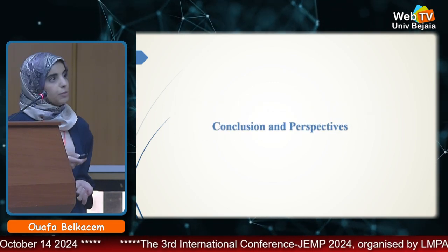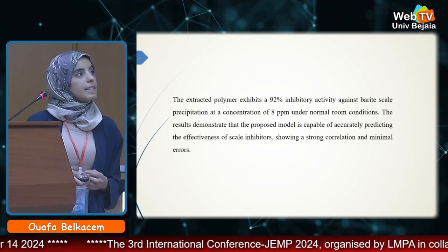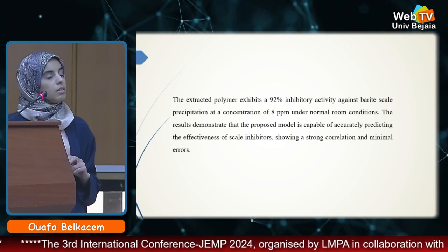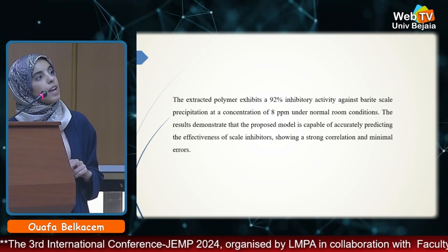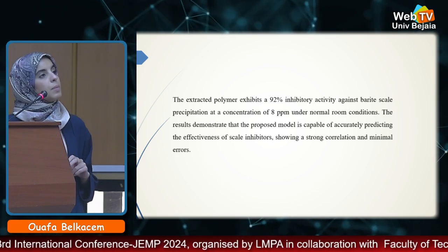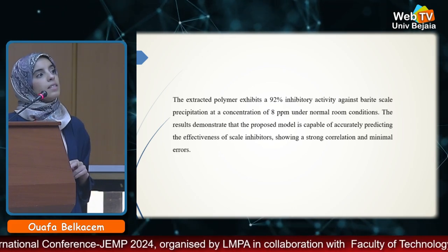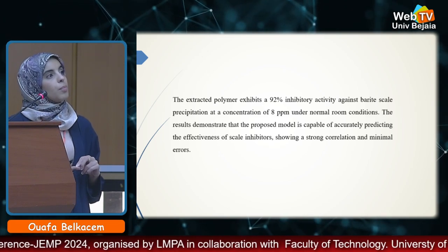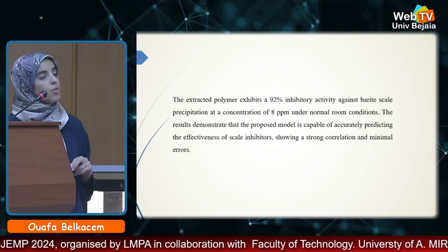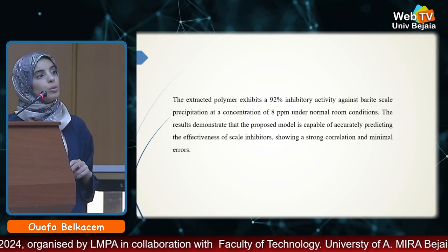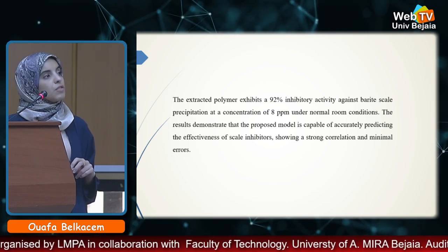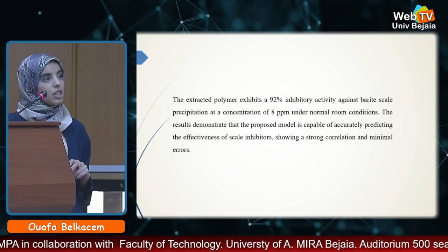Conclusion and perspective. The extracted polymer inhibits 92% at 8 ppm concentration under normal room conditions. The result demonstrates that the proposed model is capable of predicting the efficacy of scale inhibitors, showing a strong correlation and minimal errors.